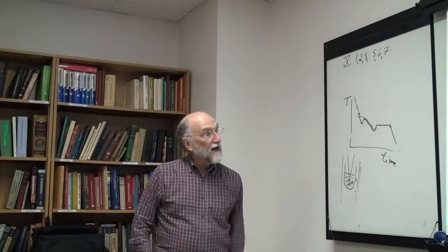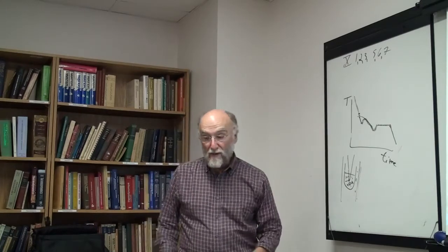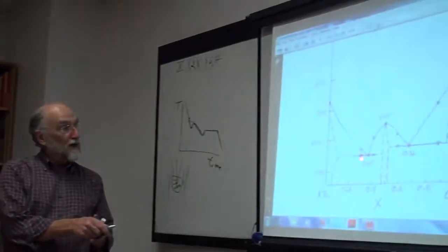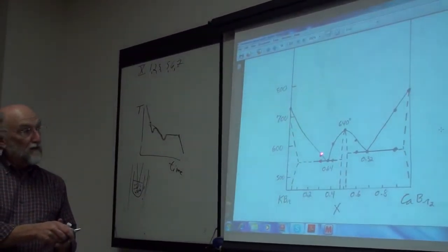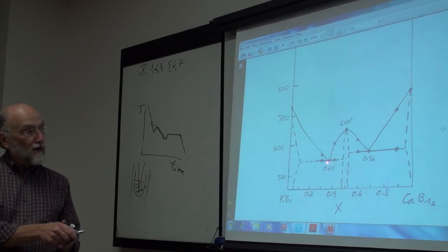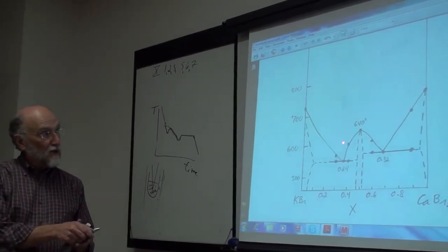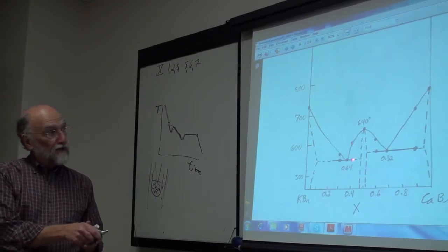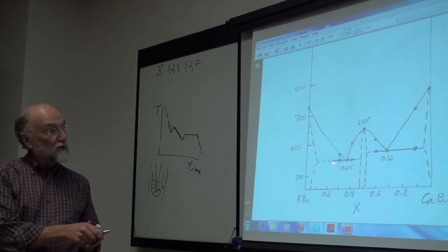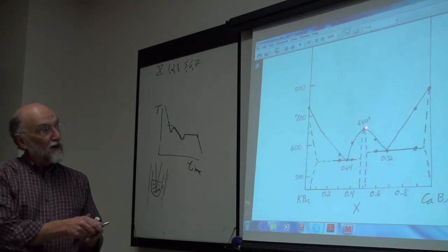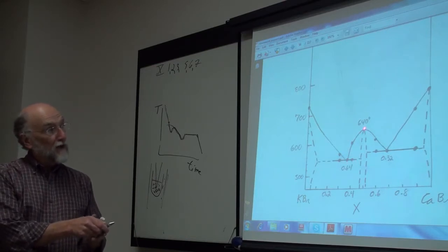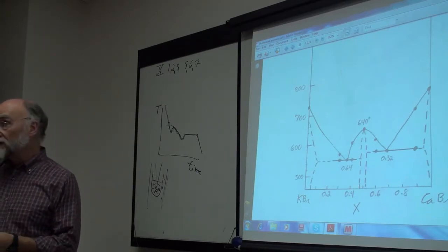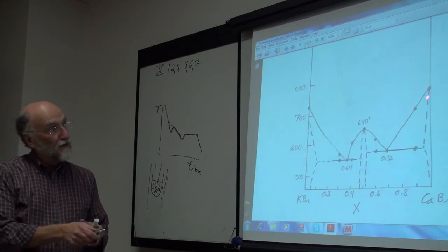Anyway, in this particular thing, I gave you some equilibrium, some ideal cooling curves. So here you had a change in slope, and you had a plateau, so this was obviously a liquidus and an invariant. Here you had just a plateau, meaning there was no primary phase, there's just the eutectic reaction. Here there's a liquidus and an invariant, but these are all the same temperature, so it's clearly the same invariant. So here, this is a quasi-unary system, the congruent melting point of a pure compound, which melts with a plateau like a pure material.